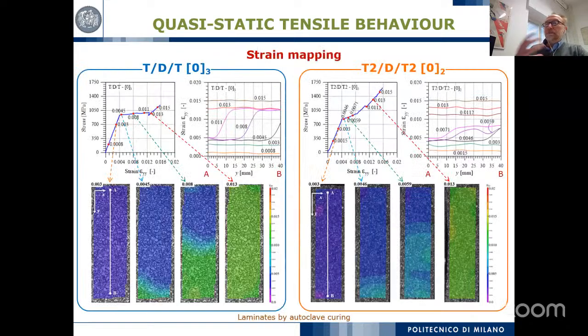Moving to the damage, that is the most important part, to understand why we have this pseudoductility and different behavior from one laminate to the other. This is a map at different strain levels for the 2-0 laminate with different sublaminates. You can see here that in the TDT sublaminate we have the beginning of a delamination, and this delamination slowly grows to cover the complete specimen.